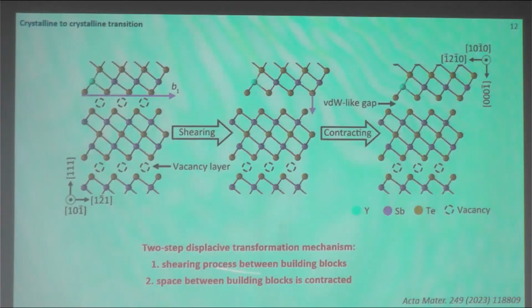And here we have two steps. One step is the shearing of the building units against each other. Here you can see this if I make the line. It can be seen maybe better here. If you take this atomic row and make the shearing, it's transformed here. And then we need to contract the system to form van der Waals-like gaps. They also showed that it's possible to go back from the stable trigonal phase to the vacancy ordered phase, but it's a more complicated process, and actually we have not observed it until now in our work.